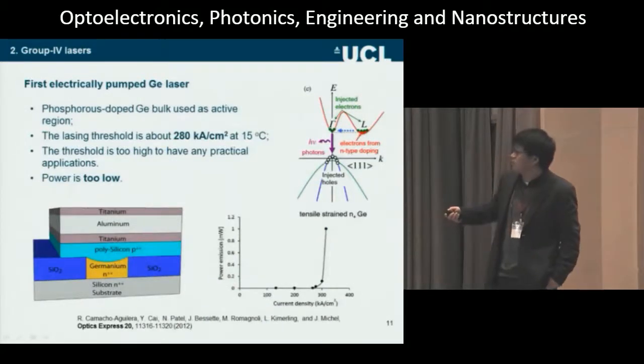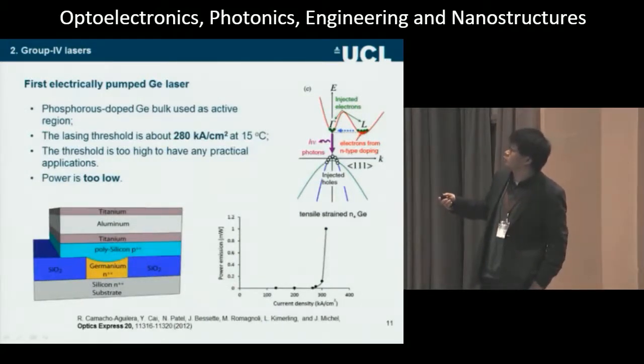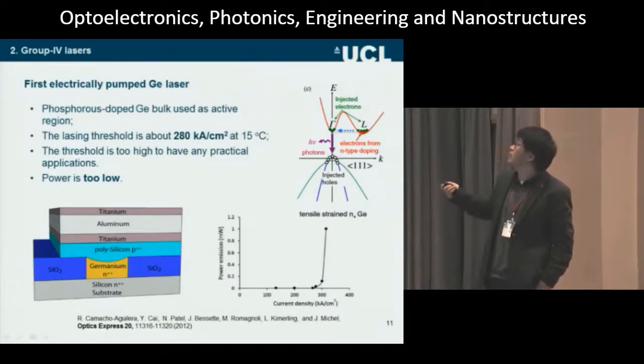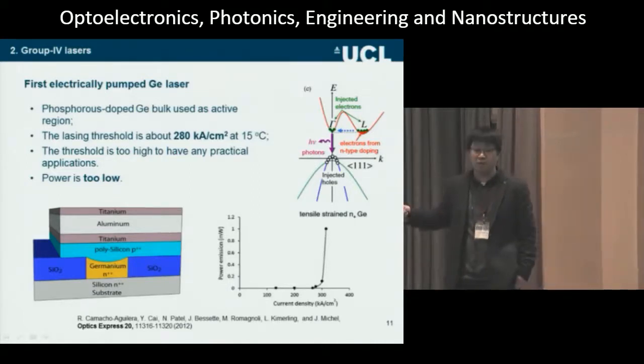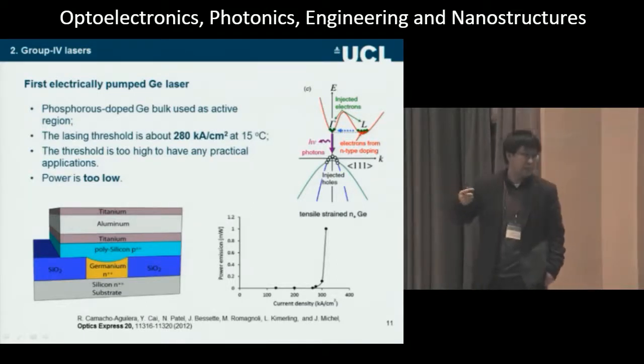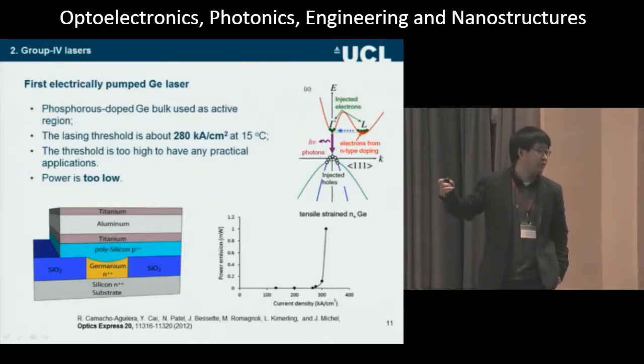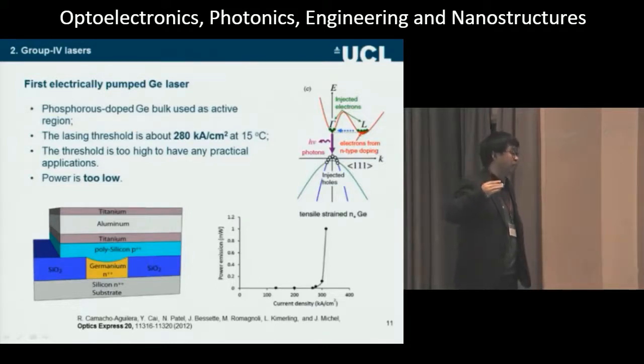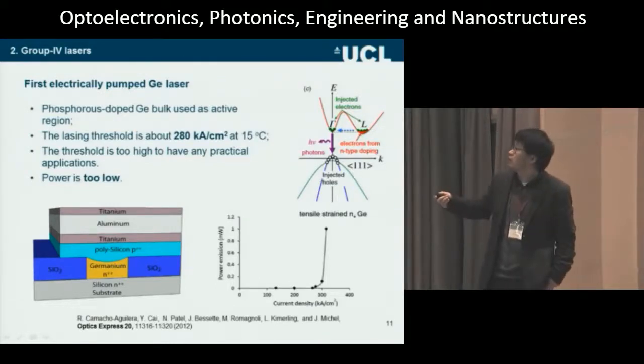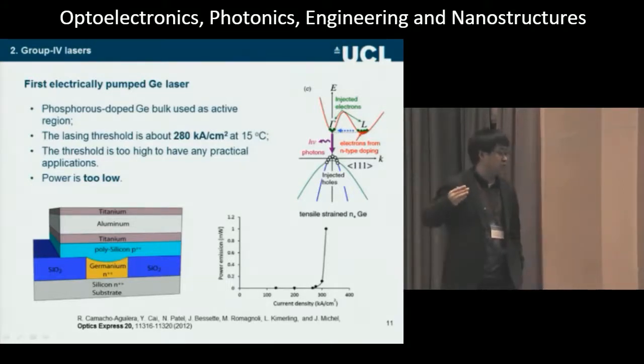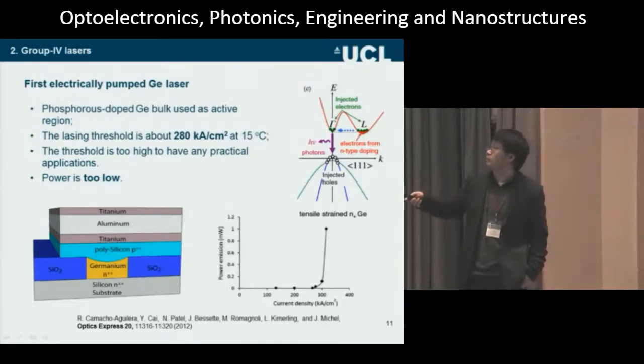Very recently, there was this paper from MIT. They use heavily doped germanium to make a more direct bandgap, like group 4 materials, and they made the first group 4 electrically pumped laser. This was published in 2012. In the first year, it was cited more than 200 times. It was very important at that time, but the threshold is 280 kA per centimeter squared at 15 degrees. This threshold, you can never put in your chips because of power consumption. The power also is too low. That was 6 years ago, and still the threshold is over 200 kA per centimeter squared.